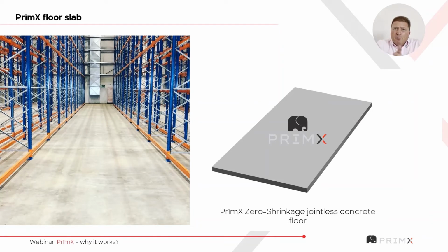So if we have two 40-metre panels side by side, the joint in the middle can open up anywhere from 8 to 16 millimetres. 20 millimetres is not uncommon. That also is a function of the aggregate grading and the aggregate type and so on and so forth.